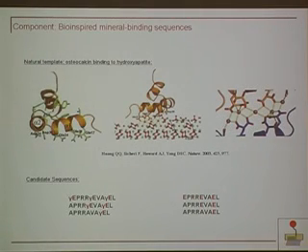The osteocalcin piece of this is really the bio-inspired piece. Osteocalcin is a protein that binds with very high affinity to hydroxyapatite in nature. This is a structure of the protein bound to the surface of a hydroxyapatite crystal, from a Nature paper published in 2003. You can see that there's this N-terminal helix that contains 3 GLA residues. GLA residues are carboxyglutamate residues. They're not found too often in nature, but they are glutamate residues that have an extra carboxylate group on them. So they are very highly charged, and therefore capable of interacting with calcium ions in the hydroxyapatite matrix.